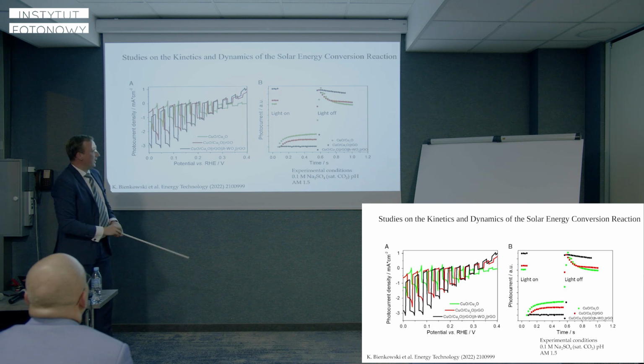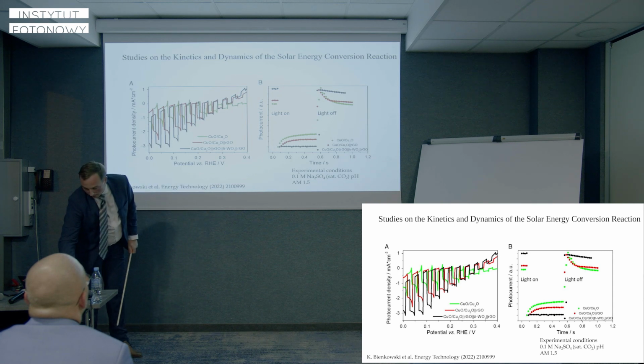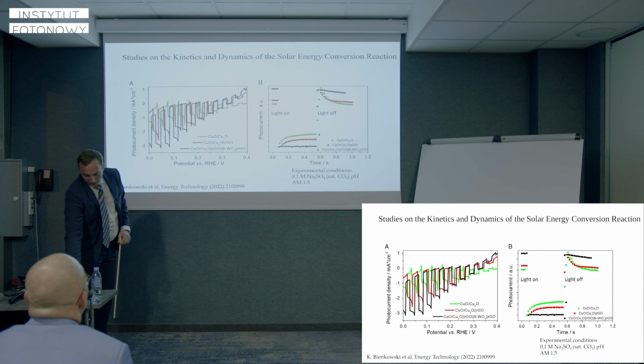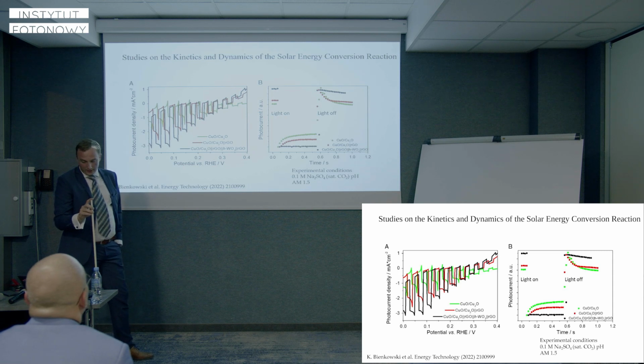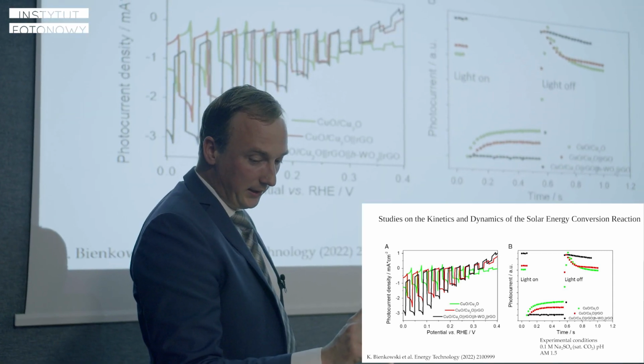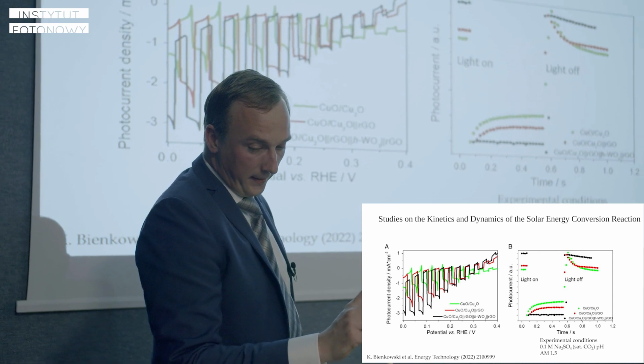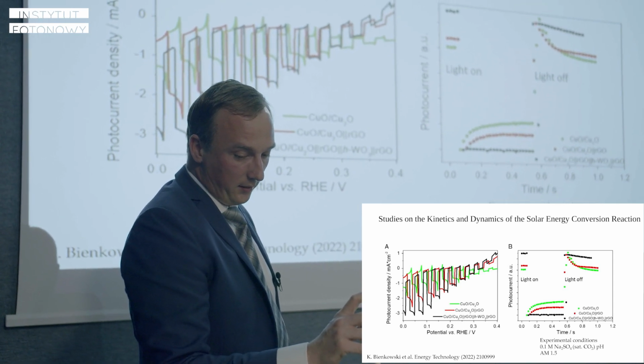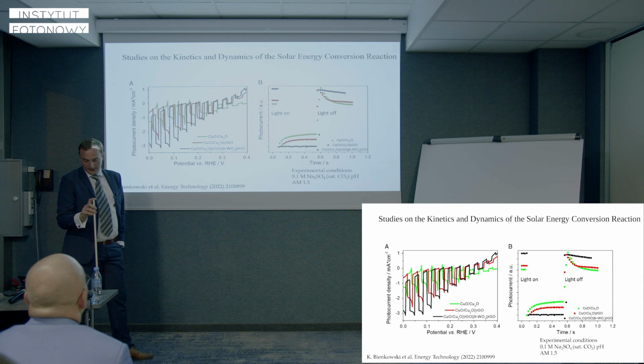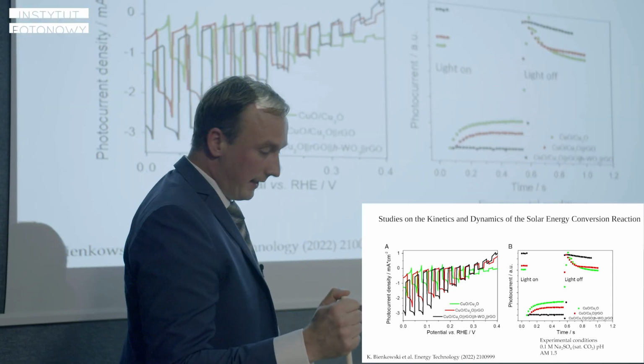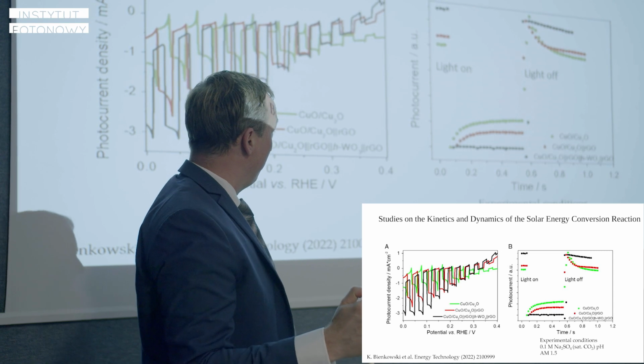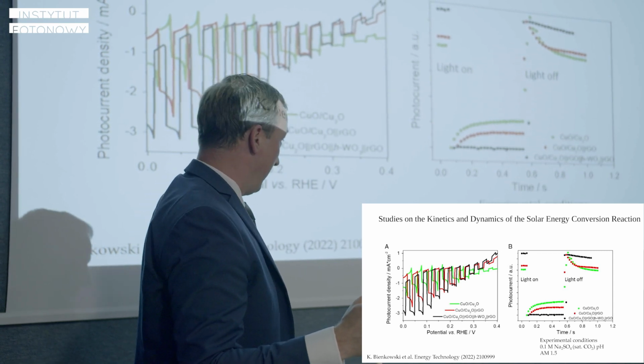Okay, the transient current measurement strongly depends on the mid and upper layers of RGO. The photocurrent plateau was reached only in the full architecture containing both the mid and upper RGO layer. When the RGO layer was absent, the photocurrent transients rapidly reduced to the dark current after 500 milliseconds, and we see that there is a very big problem with our electrode.